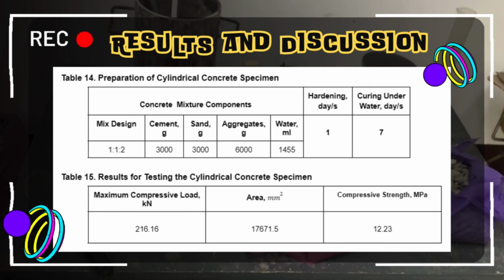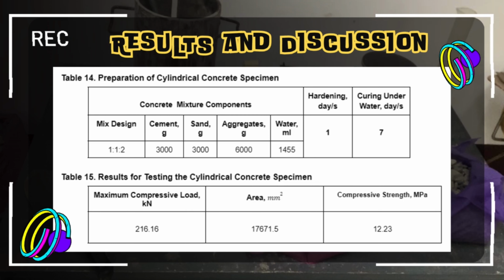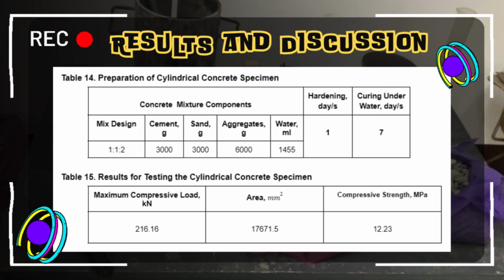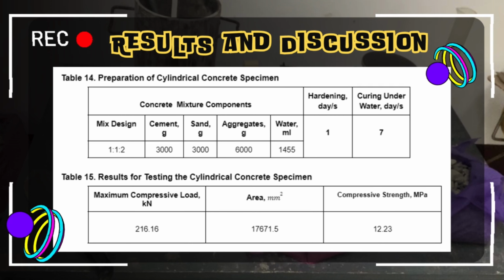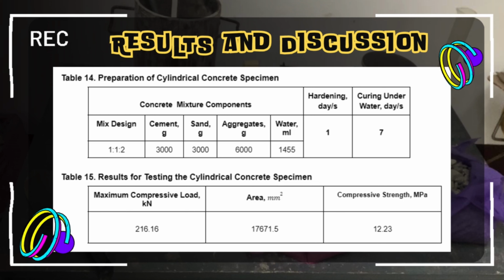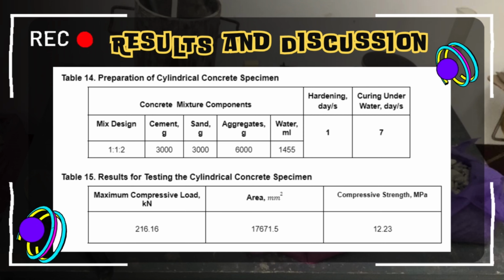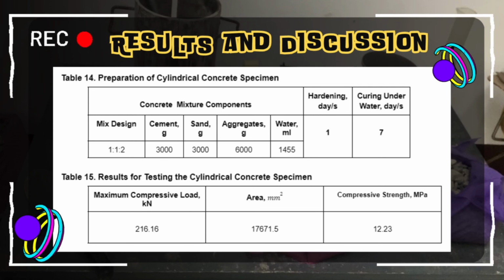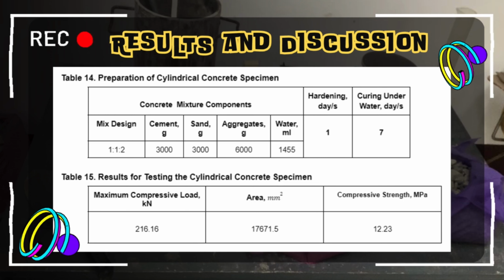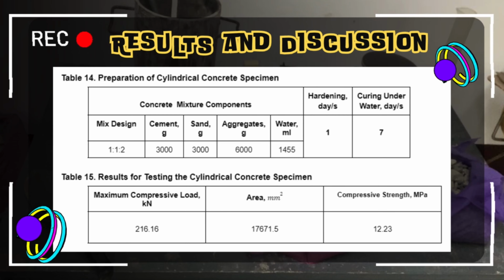This discrepancy suggests potential issues with the mix design, materials utilized, or the curing process. The primary factor believed to contribute to the lower strength is the composition of aggregates used in the concrete. It appears that there was inadequate distribution of fine and coarse aggregates in the mix, resulting in a less compact concrete cylinder despite proper tamping as outlined in the procedure.